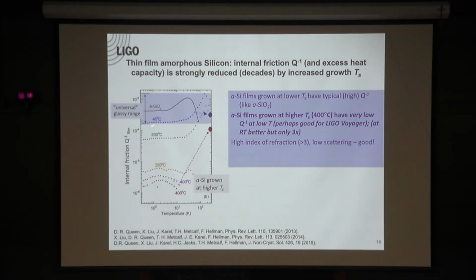So that flat region is part of the standard tunneling model. And in the standard tunneling model, we call that Q naught, for obvious reasons, it's the plateau. There actually is more complex stuff that goes on at lower temperatures. So this is all about relaxation processes in this standard tunneling model. But that plateau is proportional to the tunneling level states.